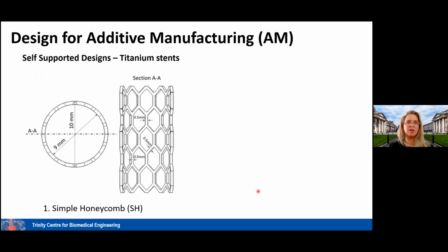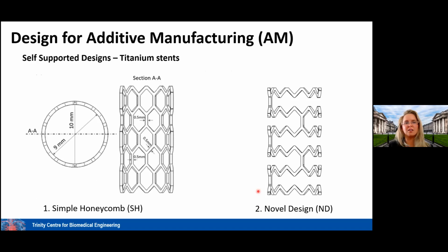So we said, let's consider that, yes, the honeycomb structure is really what we can work with in terms of printing stents. But surely there are ways that we can post-process this. We can carry out other techniques after our printing to maybe end up with something that is more flexible, as I'll show you. So something like this on the right-hand side, which is what we're calling our novel design, in this case, which is an open cell structure, which, as you can see by just looking at this, has overhangs that are way past 4 millimeters and really doesn't conform to our design guidelines. So we had to think a little bit outside the box and go, well, we want to 3D print, but perhaps we need something to modify what we can deliver with 3D printing to get what we ultimately want for delivering the best treatment for individuals, or at least to give us flexibility in design. Can we have these open cell structures?